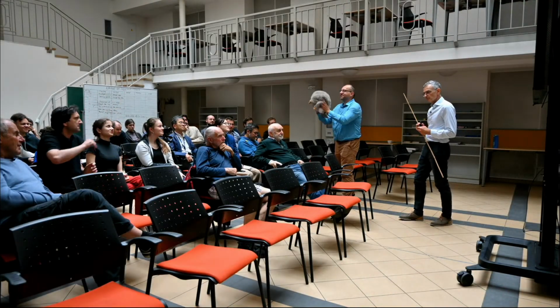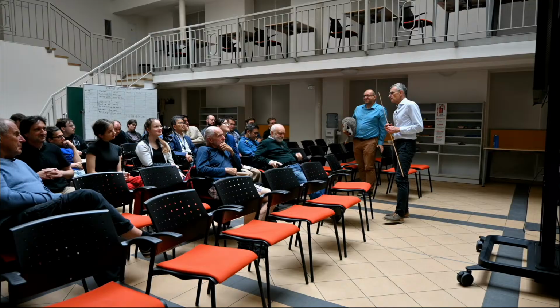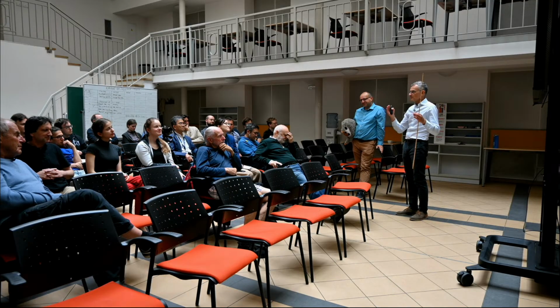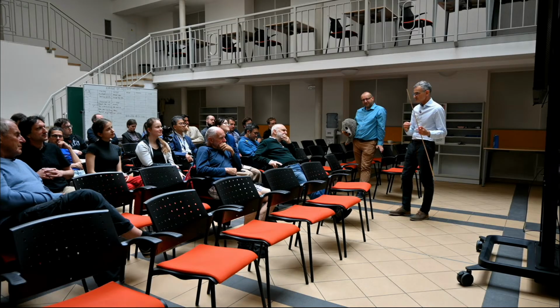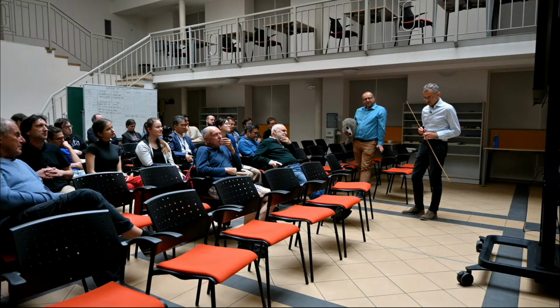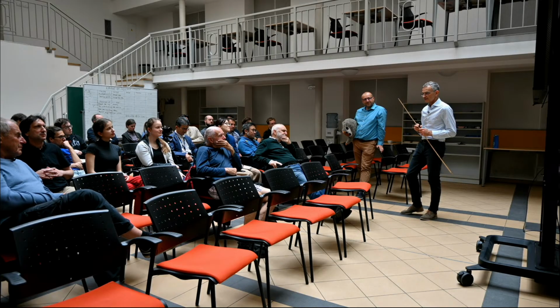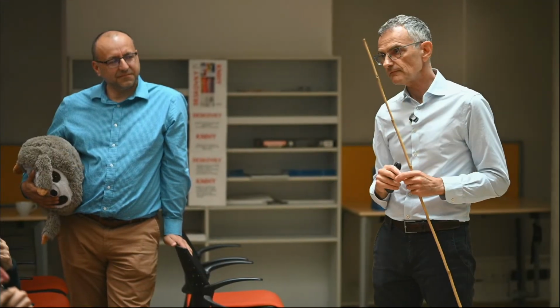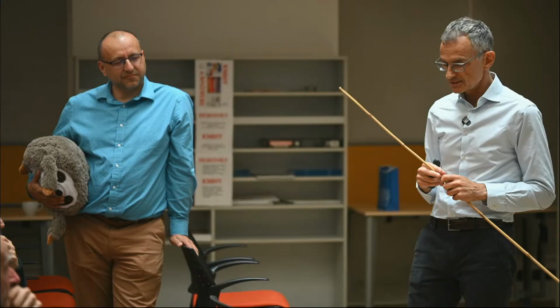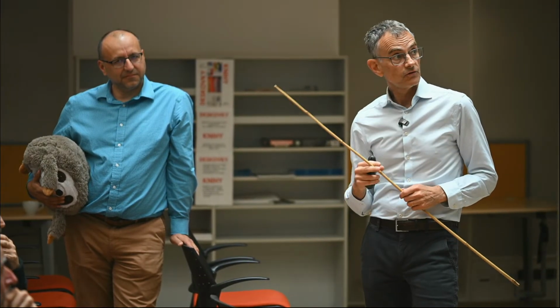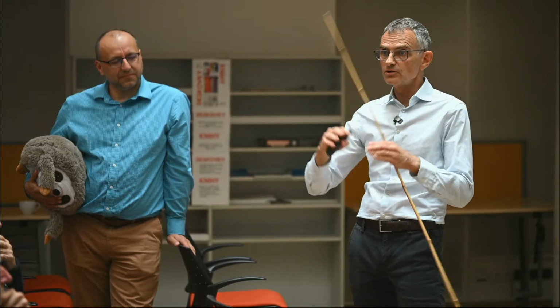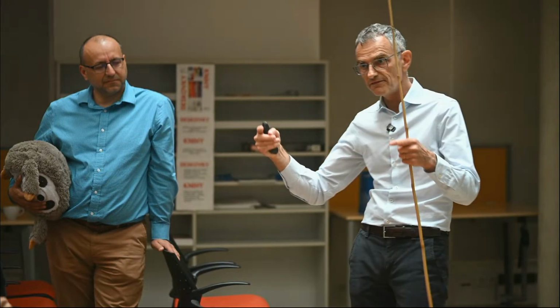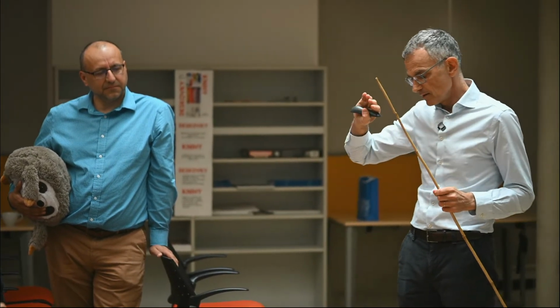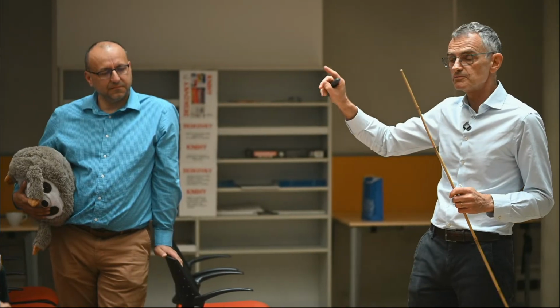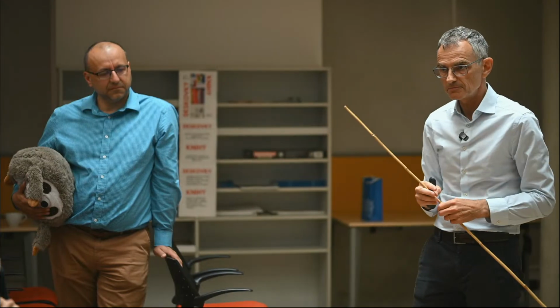Yes, thank you for the question. So the answer is yes, and there are papers published on a transformation from an altermagnet to this other phase and vice versa. We first have to define what we mean by antiferromagnet. What we mean by, let's say, a Néel antiferromagnet is a phase which is also collinear. It's also perfectly compensated, the compensation is by symmetry. But if you look into the electronic structure, it's completely spin degenerate. So you would not see the difference between a non-magnetic phase and the Néel antiferromagnetic phase if you just went to the electronic structure in momentum space, in terms of spin polarization. The bands can be different, but they will not be spin polarized.